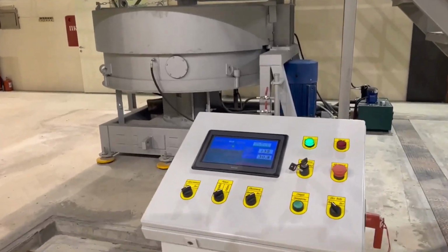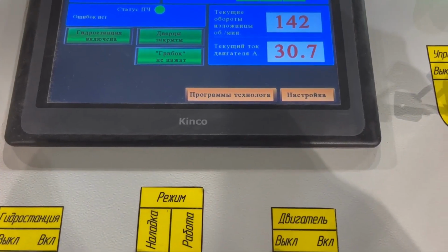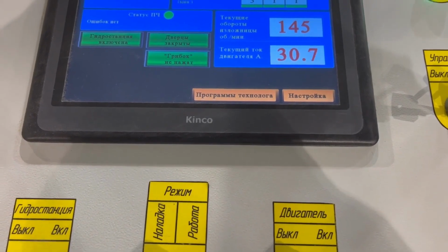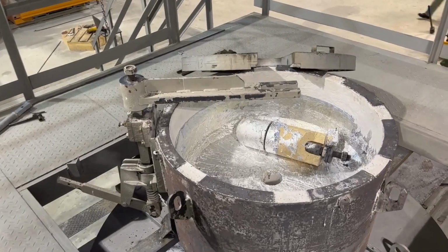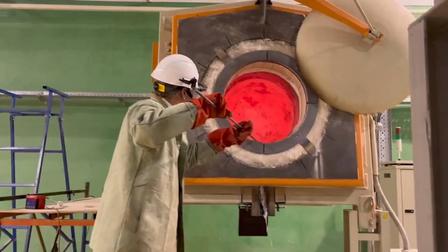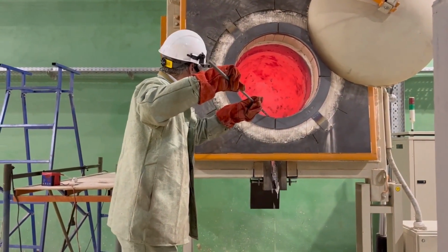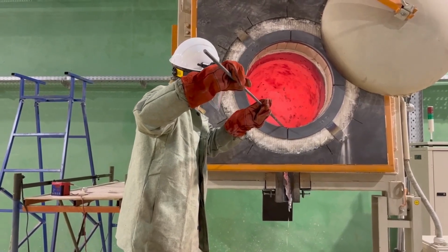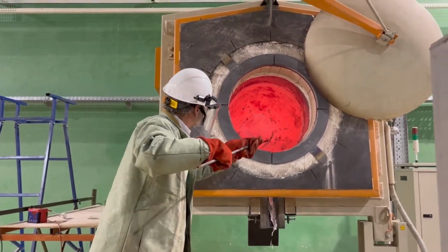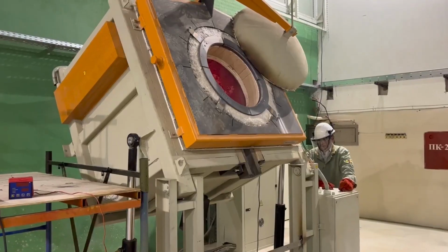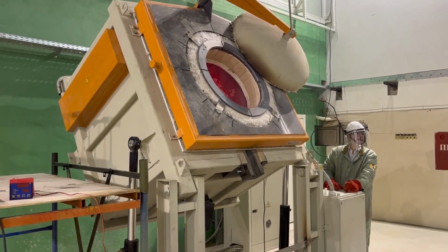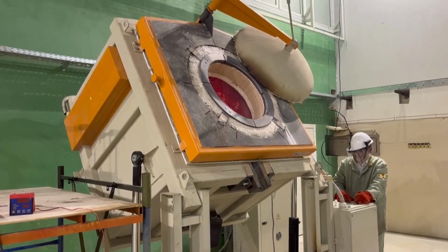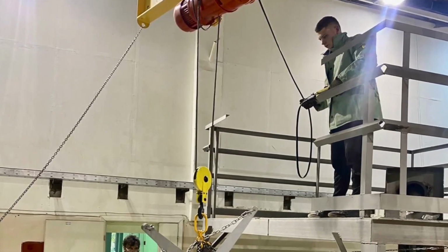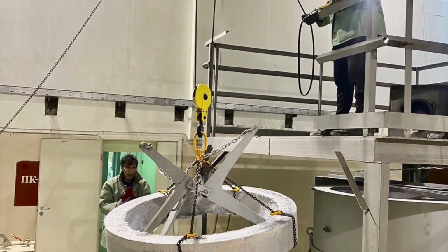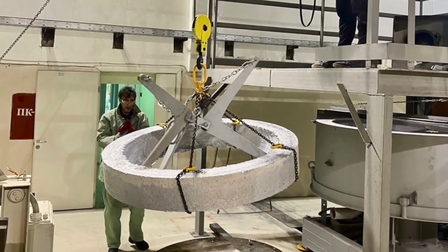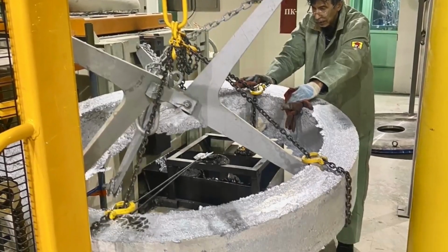The molten metal cools and solidifies against the mold wall. Cooling rates can be controlled by regulating mold temperature and rotational speed. Since the material cools from the outer surface inward, the outer layers are dense and free from defects, while any inclusions or impurities are pushed toward the center. After solidification, the casting is removed from the mold. The inner surface, which may contain impurities, is machined to achieve the desired internal diameter and remove any imperfections.